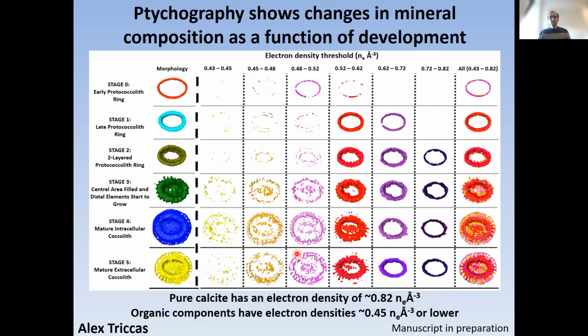because we know from the literature that the amount of organic polysaccharides that are included in the Emiliania is a few percent. So we're talking probably 2 to 5%. So it's not enough to explain these differences. But there is something happening when you're going from this stage to this stage here, which may indicate that at the very early stages, what you have is not calcite, but it's some form of calcium carbonate that is lower in density. And that could be amorphous calcium carbonate. It could be a very, very hydrated mineral.